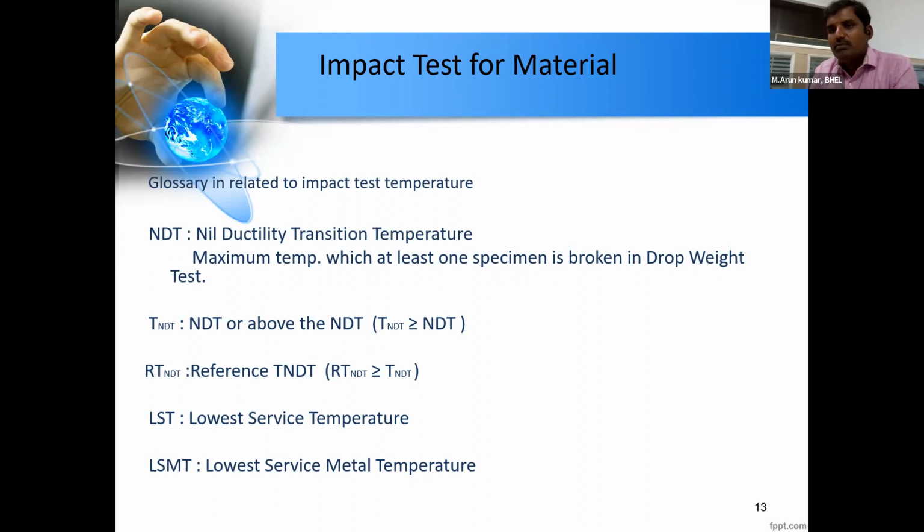After that heat treatment, they have already established minus 30 degrees Celsius, and what we are establishing is plus 20 degrees Celsius. That means we could identify around a 50 degree Celsius difference.